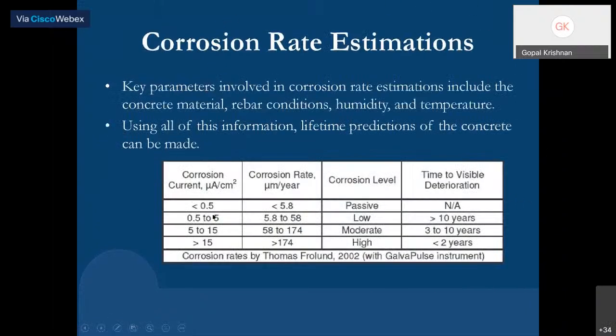When you are estimating the corrosion rate, when it is lesser than 0.5 microampere per centimeter square, that is lesser than 5.8 micrometer per year, based on that you can determine the corrosion level. It is a passive level, so there is no deterioration taking place, no visual deterioration. Then 0.5 to 5 microampere per centimeter square corrosion happens, with a rate of 5.8 to 58 micrometer per year.